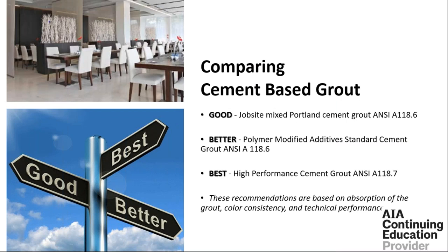So we compare the cement-based grout: the basic 118.6, that's just the sand and cement, then the polymer modified. Adding the polymer to the basic Portland cement grout is better. And the high performance, we gave a lot of examples of why you would use the 118.7 grout: fast setting, highly hydrated, just a great product all the way around. So this is good, better, best. And what are these based on? They're based on absorption of the grout, consistency of color, and the technical performance.